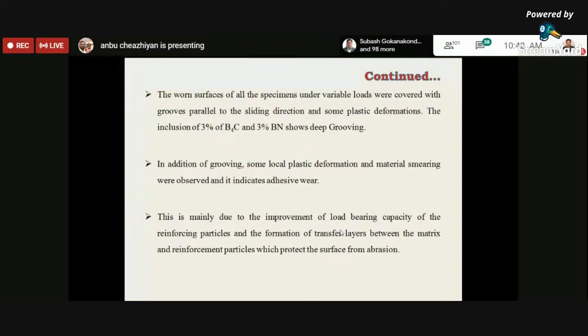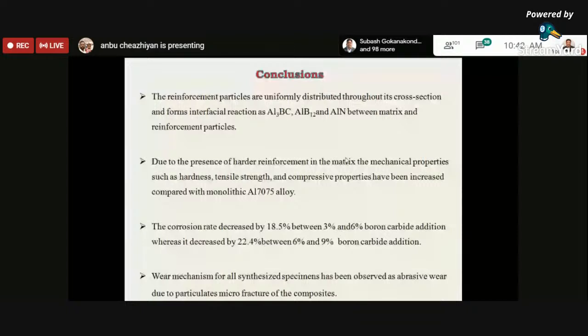So from this, it has been concluded that the inclusion of boron carbide and boron nitride nano-sized particles are uniformly distributed in the matrix, and a few clusters were found around the regions of aluminum grain boundaries, and it forms interfacial reactions such as Al3BC, AlB12, and AlN. So this acts as a strengthening mechanism to enhance the mechanical properties of the composites. Also, due to the presence of harder reinforcement, the mechanical properties such as tensile strength and hardness of the composite have increased compared with the monolithic material.